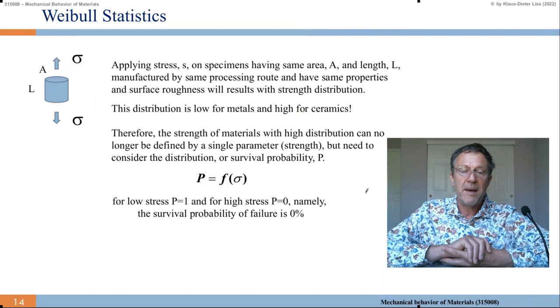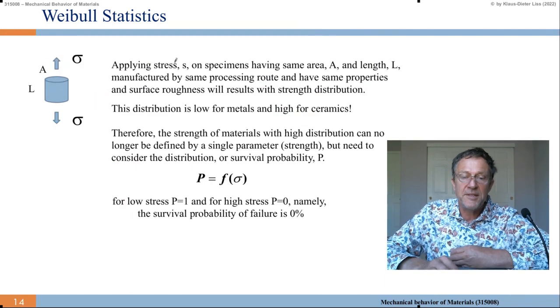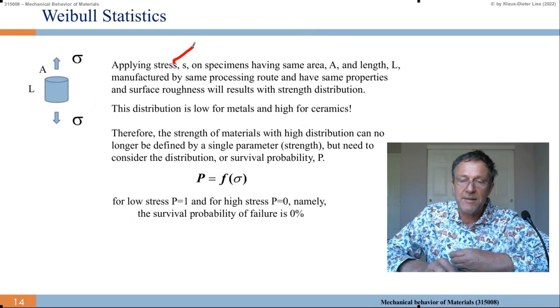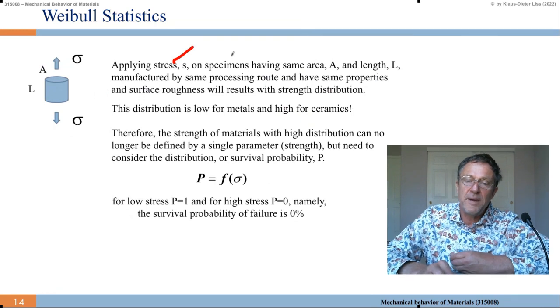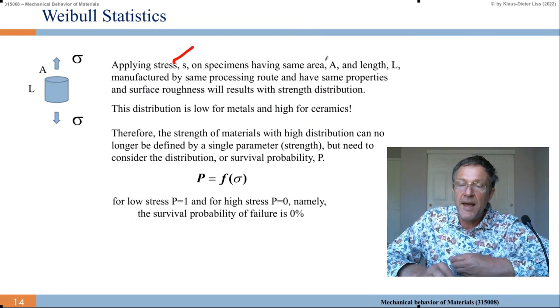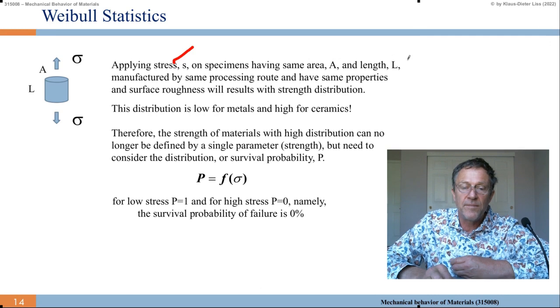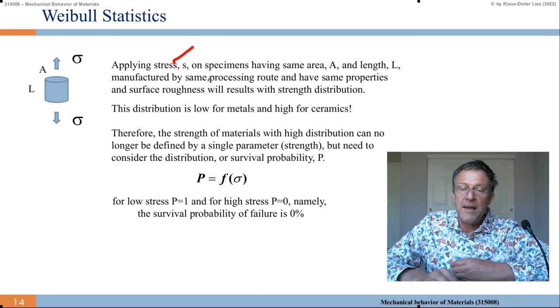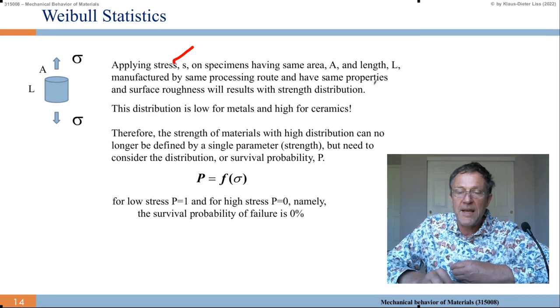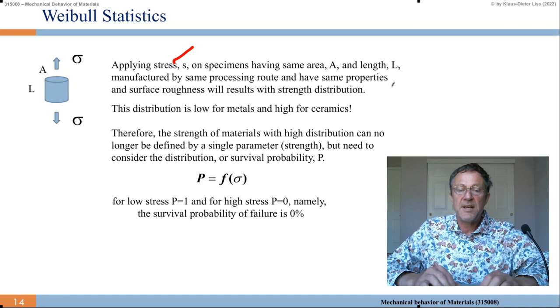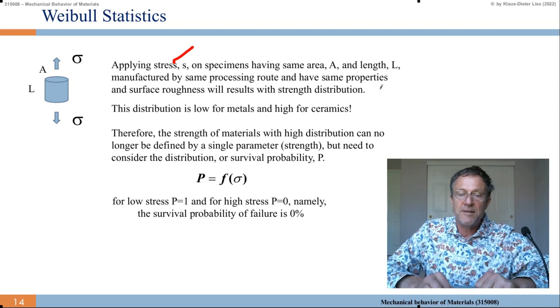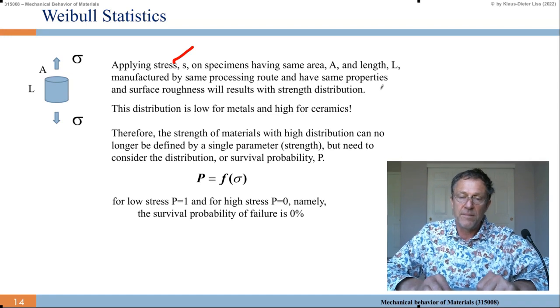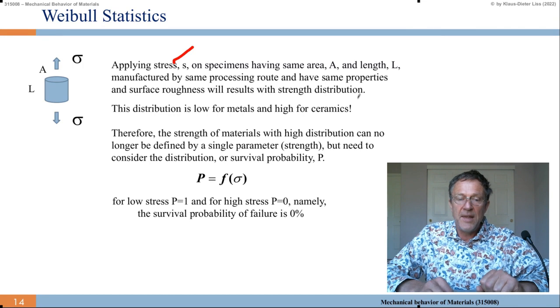You do the experiments by applying a stress S, in this case it should be sigma, on specimens having the same area A and the length L, manufactured by the same processing route, and having the same properties and surface roughness. This will result in a strength distribution. So make them all the same. And this distribution is low for metals and high for ceramics. That's what I said already.